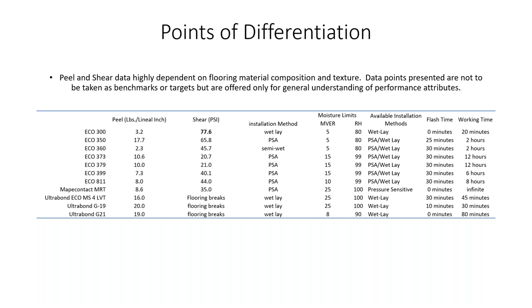If it's going to do anything, it's going to go sideways. But pulling it off the floor, it really is an indication of how brittle this adhesive is. And that could essentially be an issue with the underlayment breaking or whatever. But the shear values are important. That's 77 to 80 PSI. So this is probably one of the largest numbers we have for shear strength and will give you one of the best performances you can get out of controlling movement by getting something that's a high shear strength material.